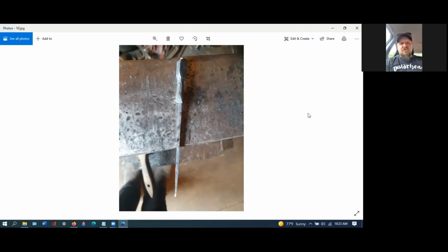But actually, before I quench, sorry, I'll thermal cycle. I'll heat the steel up to critical, and then I'll allow it to cool slowly. That shrinks the grain of the steel and makes it stronger. And then obviously you temper it. Those were tempered back to a dark straw, which softens the steel up again, because if you left it hard, it'd be like glass. If I hit it with a hammer, it'd shatter.